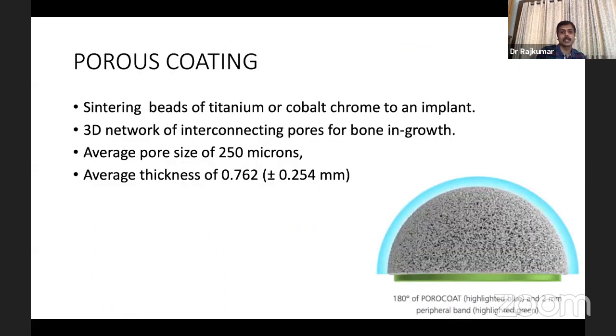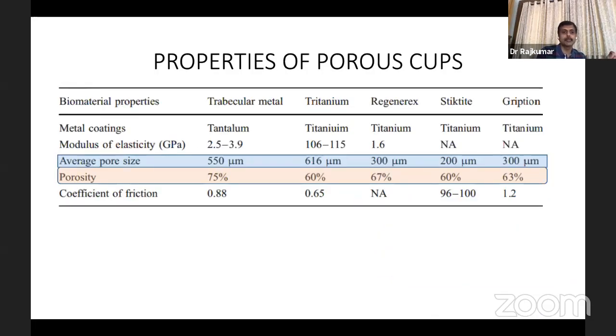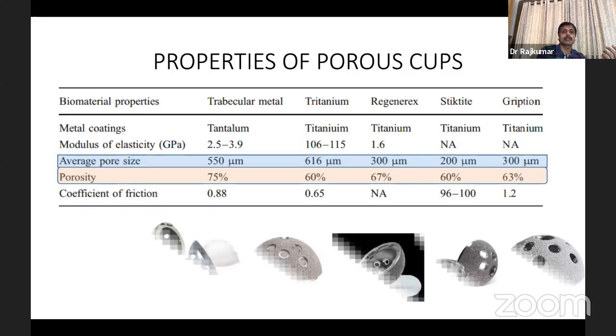As I told already about the porosity, the better the porosity, the better the stability and the bony ingrowth. If you look at the various metals, trabecular metals, titanium, Gription, all these materials, the porosity is there, like 75% to 65%. The trabecular metal has got the highest porosity. That is why in revision cases, we tend to use more of trabecular metal implants.